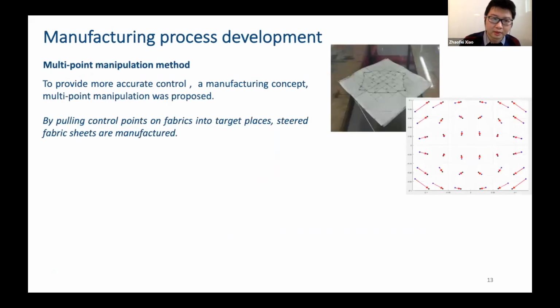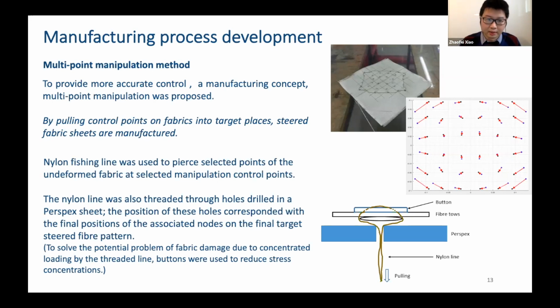we proposed a new method, which is called the multi-point manipulation method. So the idea is by pulling some control points within or on the perimeter of the fabric to their target position, we can achieve the steered fabric sheets. At each selected manipulation point, we use nylon line to pierce through those points, and those nylon lines are also threaded through some holes drilled in a Perspex sheet. The positions of those holes are the final position of the associated node on the final target steered pattern. And to avoid potential damage around the control point, we also thread a button on the fabric to reduce the stress concentration.